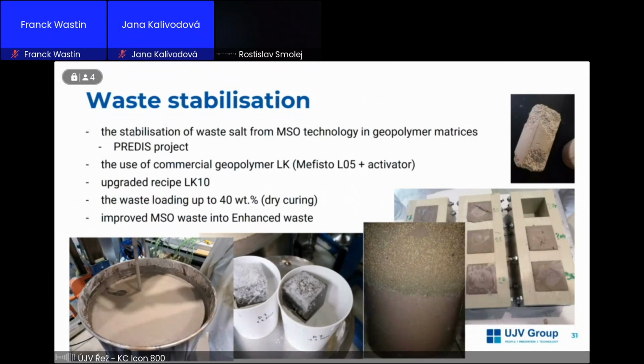So what stabilization have we done in our lab and in our group? As I've mentioned, we are using the geopolymer matrices, mainly the geopolymer LK, which is the precursor Mefisto L05 and then an activator. We have taken that recipe and improved it a little bit for the LK10, because in the previous project our work was mainly focused on the stabilization of the salts from the molten salt oxidation, and we ended up with a waste loading of up to 40% waste with the dry curing, which is very good. And we also improved the molten salt oxidation waste into something called enhanced waste, which practically improved the final form of the stabilization.